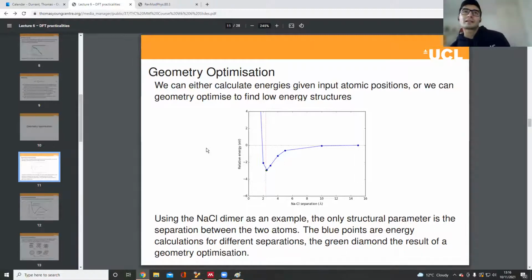A lot of molecular dynamics force fields are produced by fitting to DFT data. As always, the potential will describe what you fit it to most of the time. So we wouldn't expect that if we fitted an MD force field to this curve it would reproduce everything to do with sodium and chloride interactions, but it would produce the right separation of this dimer.